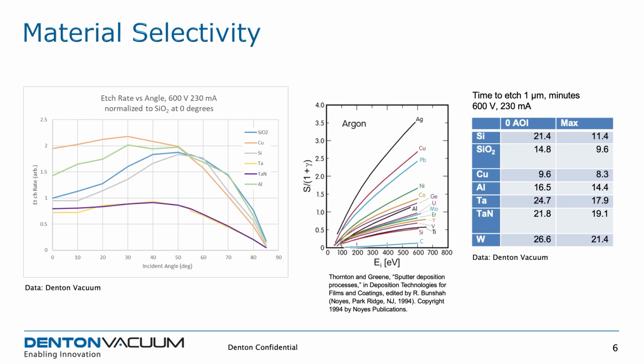So you can see on this chart, which is data that I took, if you go to around 50 degrees to 55 degrees, the etch rate for silicon oxide and copper are the same. So that means if you have copper traces within a silicon oxide matrix, you can simply tilt the machine to 50 degrees and you can keep etching planar through the device.